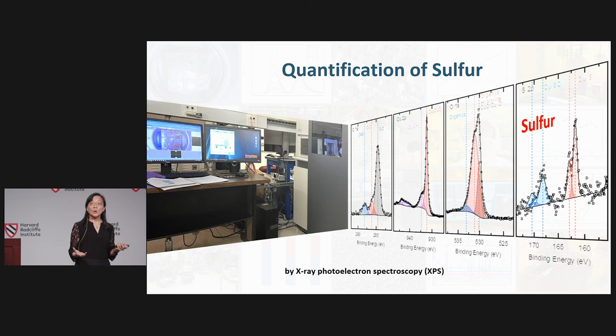Because we're looking at the poisoning effect, I have to quantify the sulfur. I needed to know how much sulfur there is and in what chemical environment it is in. So I use a technique called X-ray photoelectron spectroscopy. As shown here, I can measure the concentration and the chemical bonding state of each of the elements on the surface, including sulfur. Once I have this information, then we monitor this concentration as we do the electrochemical experiment to recover the activity of the copper to see how effective we are.